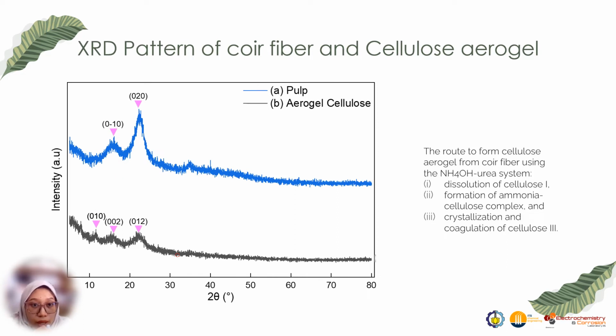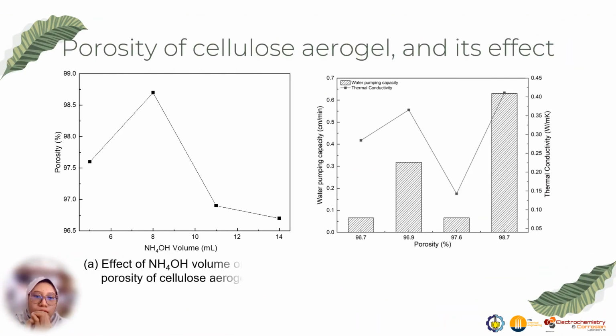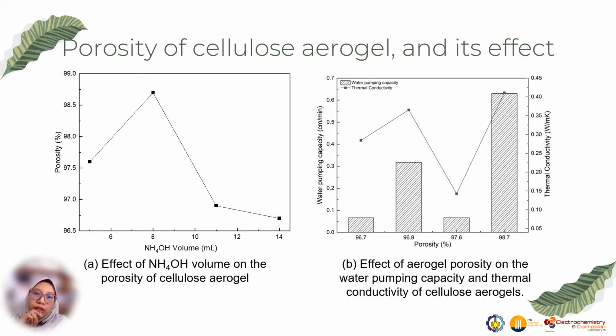A different diffraction pattern was obtained for cellulose aerogel, in which the peaks that appeared previously in the diffraction pattern of the pulp disappeared. The peaks were replaced by three characteristic peaks at 11.592 degree, 16.021 degree, and 22.170 degree, which match the standard pattern of cellulose type 3. The maximum porosity was obtained at ammonia volume of 8 milliliter with a porosity of approximately 98.7%.